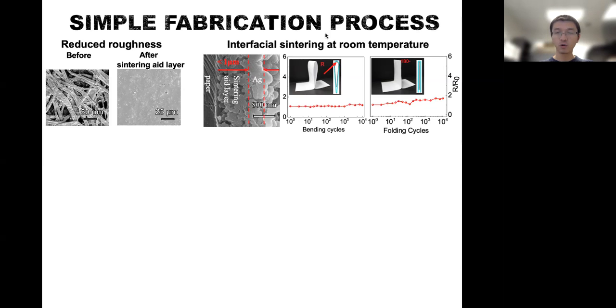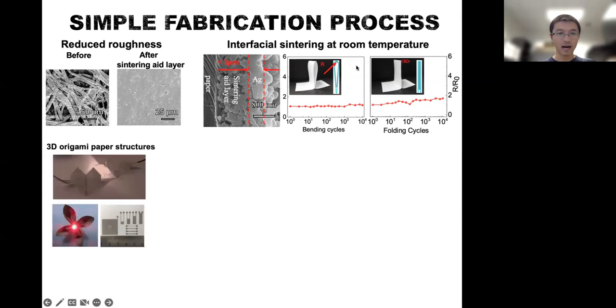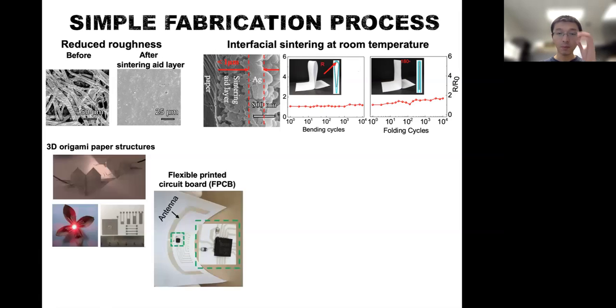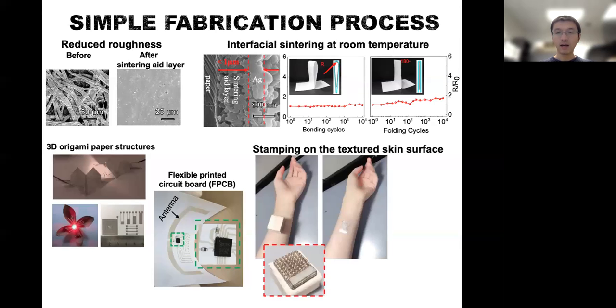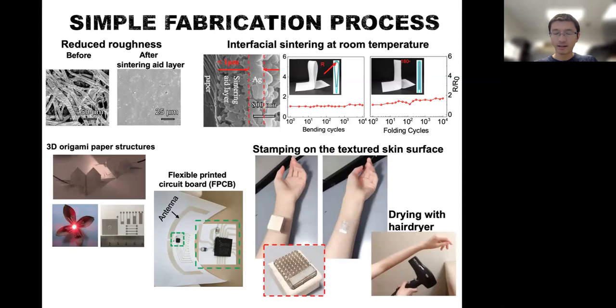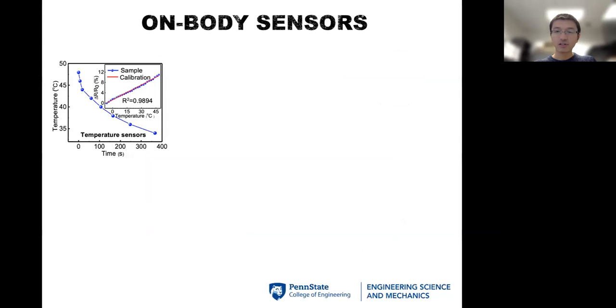So we can not only do bending, folding, and origami design, but also integrate our sensors and the wireless transmission modules on that piece of paper. And we can also do that on the skin surface. And this is actually very simple. We can use, for example, printing, stamping on the textured skin surface. Of course, this ink will have a lot of solvent inside. So to evaporate that, we simply use a hair dryer, and then you can evaporate the solvent, leaving the nanoparticle-based device on the skin surface.